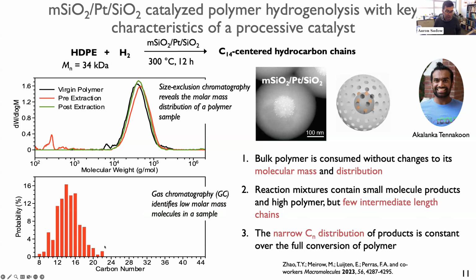And you can see this rather narrow Gaussian distribution. So this has all of the properties that we attribute to a processive kind of deconstruction. The bulk polymer is consumed without change to the molecular weight, that's shown by the SEC. The reaction mixture contains high polymer, low molecular weight species, and very little in between. And then the products are a relatively narrow distribution, and that doesn't change over the course of the conversion.